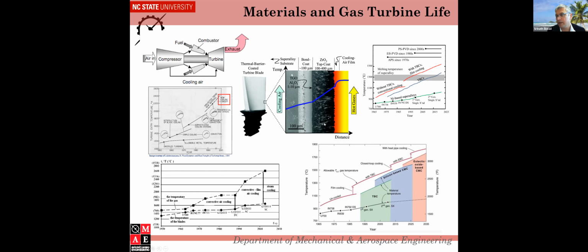So the coating actually is one of the best inventions in the past 20 years that has helped with cooling. And it also allows us to go to higher temperatures. So as you can see, with TBCs and film cooling, we are already hitting about 1500 to 1700 degrees C. And there is a lot more history behind it.